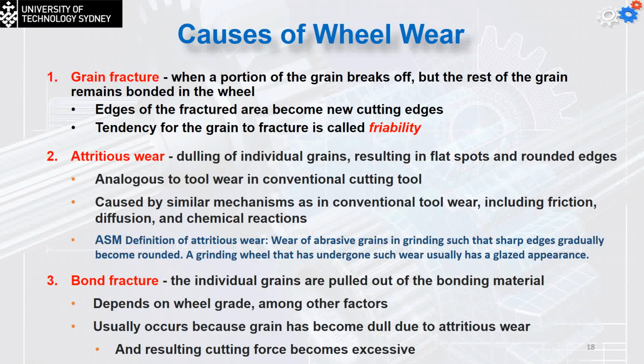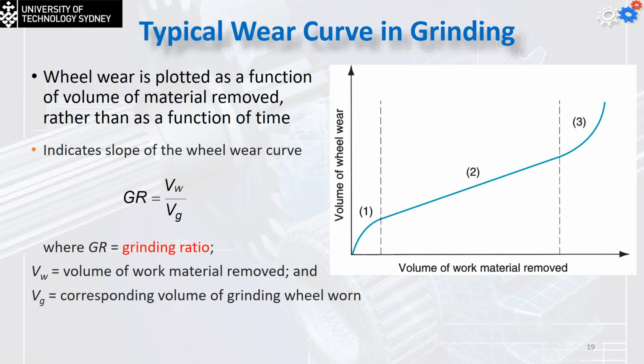So the diagram of the tool life or the wheel life is going to be something similar to what we have in the case of the cutting tool. We're going to have the initial wear, the continuous progressing wear, then the accelerated wear until we reach the final tool life or the wheel life. So we can simply get the wheel wear curve from GR, which is the grinding ratio, equal to VW, which is the volume of the work material removed, divided by VG, which is the corresponding volume of the grinding wheel worn.